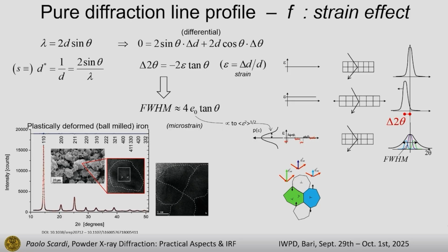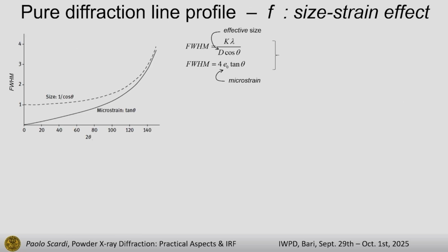Okay, so now what do we have so far? Two equations. One is the Scherrer equation. The full width of the peak gives you the effective size, okay? That is the L-vol thing I told you before. Then you have the other equation, that the full width is also related to this microstrain term. So it is very human when you have two things, you say, oh, what should I do? Let's try to add them together. It's a great temptation. And this method has been used so many times and is still very popular.